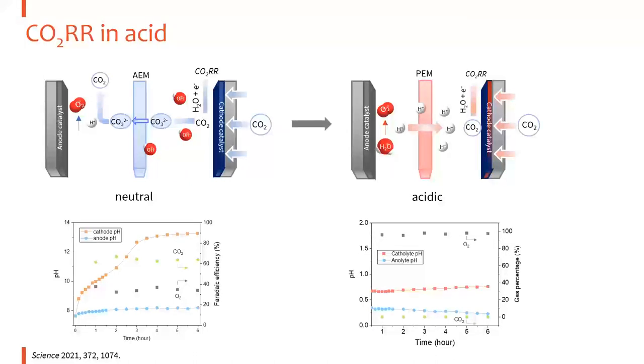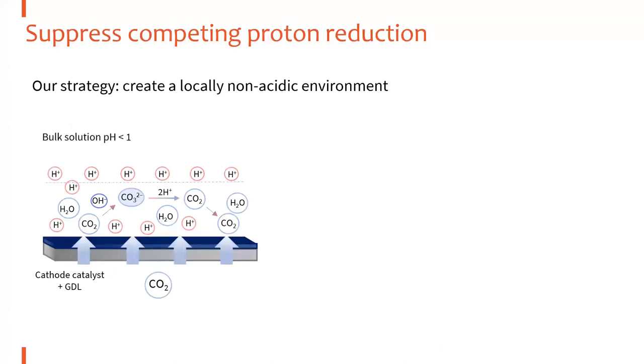But for the cathode side, our intention is to reduce CO2, and what we observe is only hydrogen evolution. This is not so difficult to understand, because we are working under strongly acidic conditions, and the reduction of protons is much easier and we have a lot of protons. So we expect to generate a lot of hydrogen from the cathode. So how can we suppress the competing proton reduction while improving the CO2 reduction?